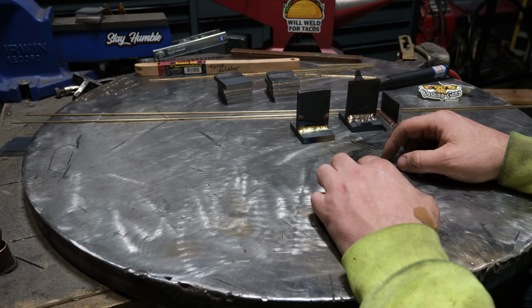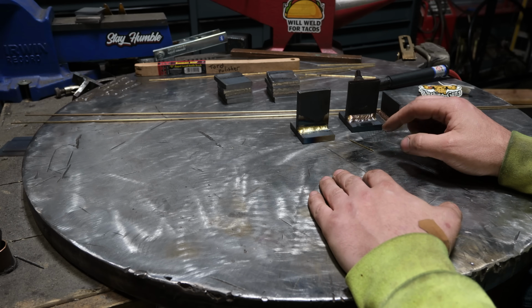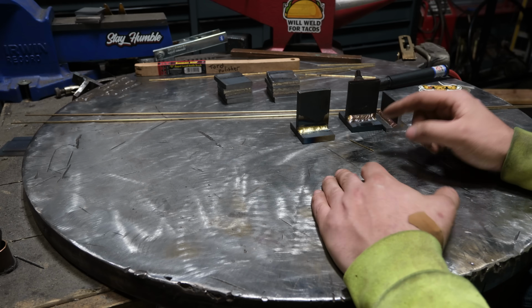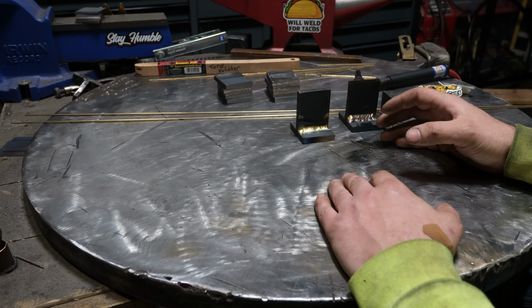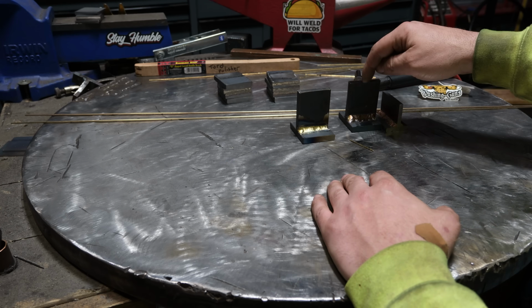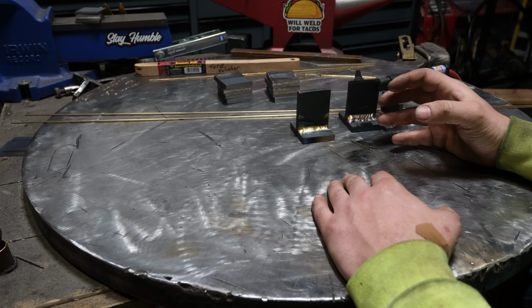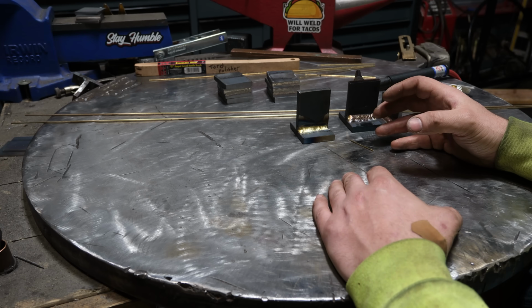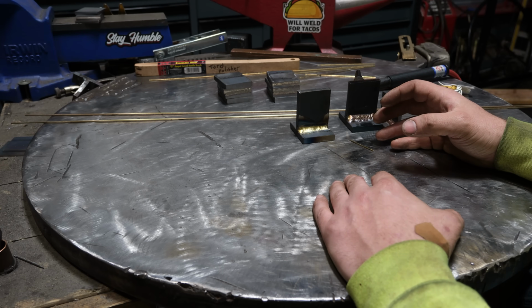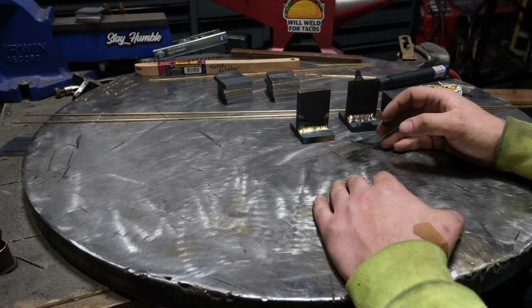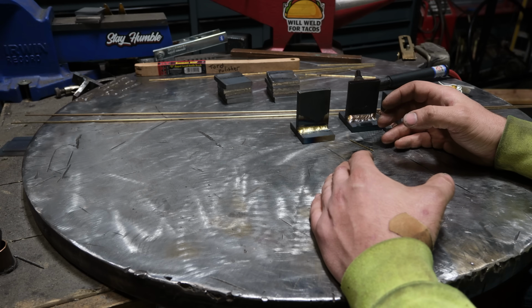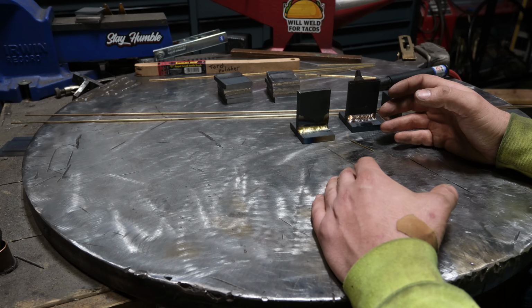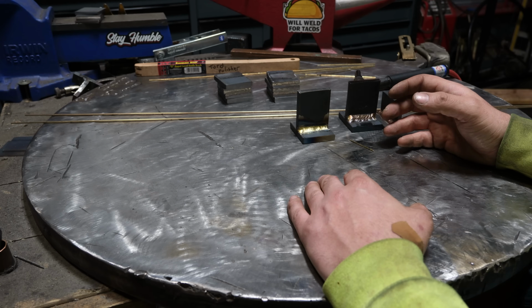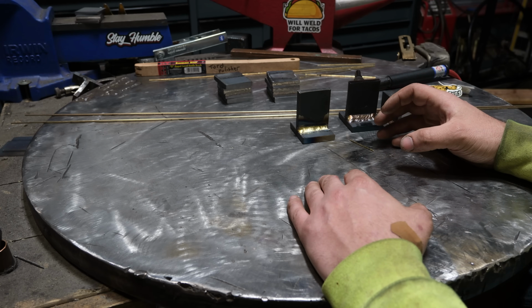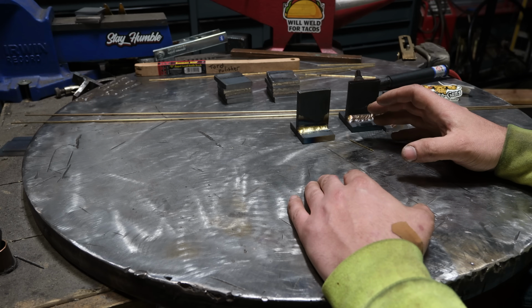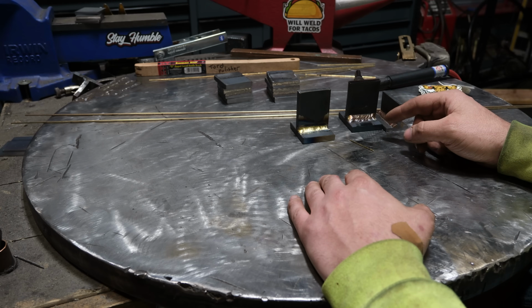Now that you understand a little bit more about that, I'm going to talk really quickly about actual practical uses for this stuff. One of the great things with bronzes and brazing is that since you're not melting your base material, you can join materials that you would never ever be able to weld together under conventional circumstances. Say like titanium to steel. You could actually do that with bronze brazing, versus if you attempt to weld it, it doesn't work. The titanium is more or less going to crumble. So it opens up a whole host of things that you can do regarding mismatching materials.